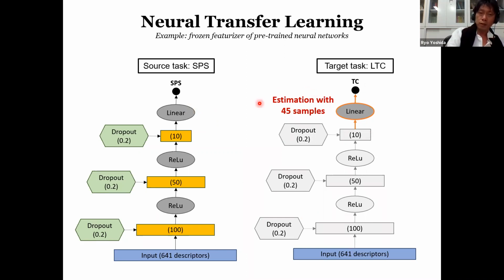To be specific, the subnetwork of the pre-trained model other than the top layer is copied to the target task. The parameters of the linear model in the top layer were estimated using the 45 samples of thermal conductivity. This is what we did, and we did nothing special other than this. I only used the conventional workflow of transfer learning.